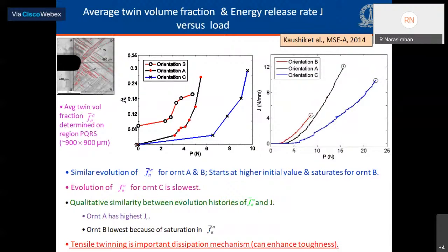We quantified the average twin area fraction as a function of load, as I described earlier, by marking out a rectangular region about 900 microns in size, a very large region, and then evaluated the average twin area fraction using the ImageJ software and plotted it against load corresponding to the three orientations. That is the figure which you see on the left side. And the right side is the energy release rate, J, plotted as a function of load.